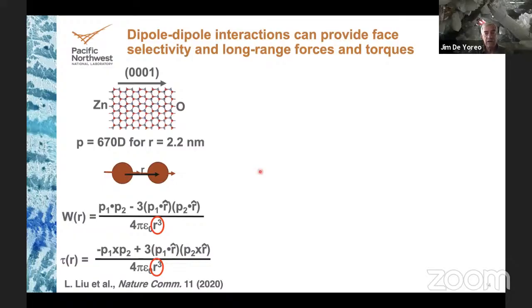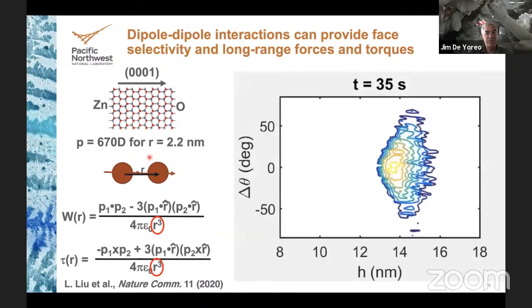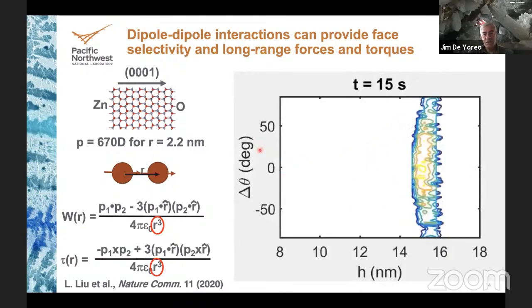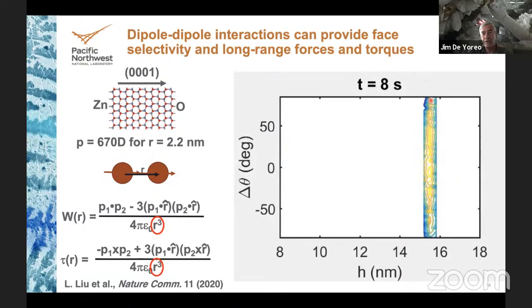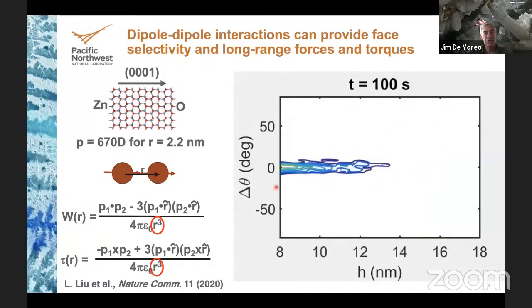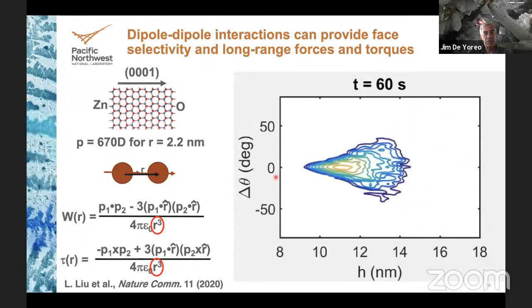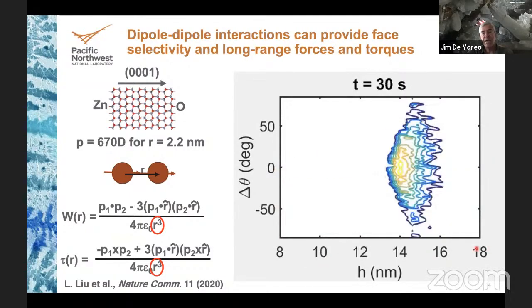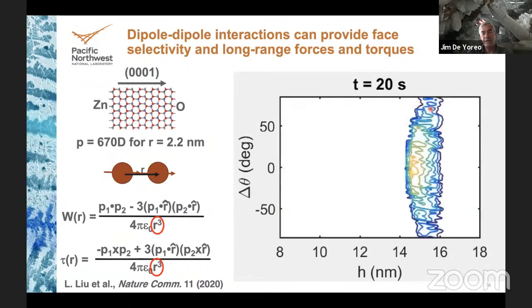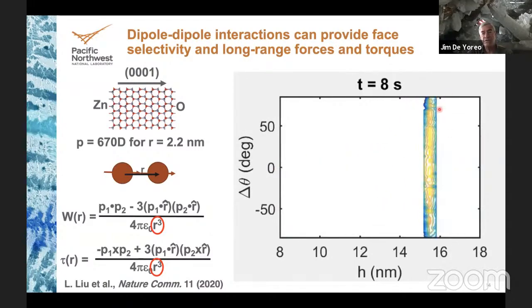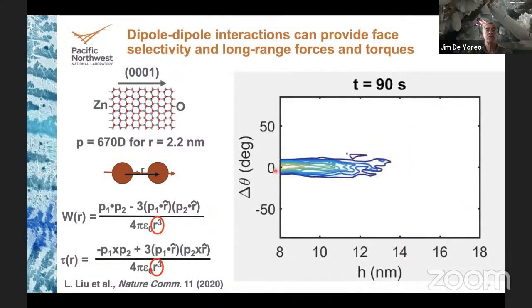And so Greg Schenter ran Langevin dynamics simulations and looked at particles that were at large separation with dipole moments of this magnitude, and started them out at a whole range of relative orientations. You see, this axis is the relative orientation of the particle relative to a surface, and this is the separation. Started all the particles out beyond 15 nanometers. And what he found is they rapidly rotate themselves into orientation or are pulled together.